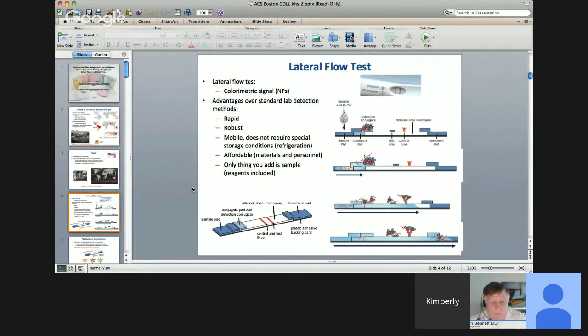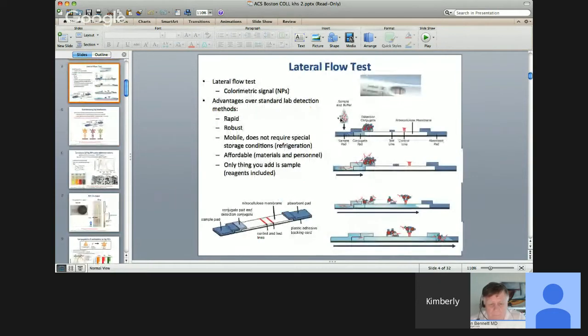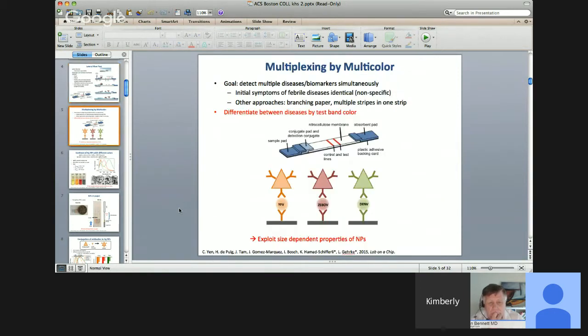So, okay, this is the lateral flow test, and you can see that this colored test line that shows up is due to the presence of the nanoparticles. Typically what you do is you just add the sample, no other special reagents, and then it runs through. And this whole thing doesn't have to be refrigerated, so there's no cold chain required to transport them. These can be manufactured in large quantities, and people already have done it for diseases, but there is none that exists for dengue, and people are trying to develop ones for Ebola, and we saw some examples of it in the literature already.